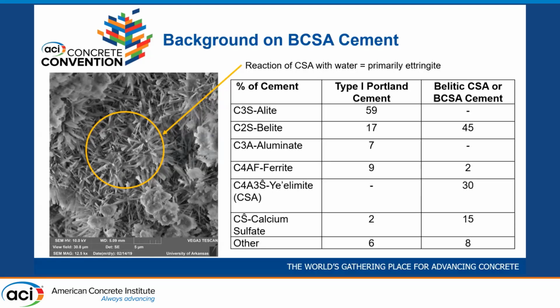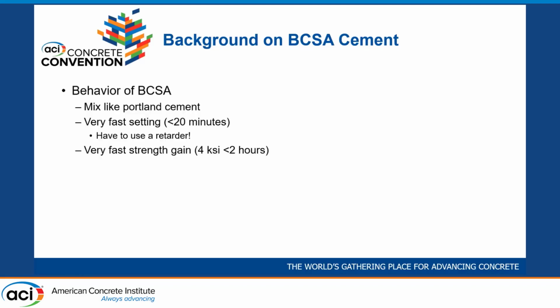So for BCSA cement, I've got a comparison here of Portland cement and BCSA in terms of their composition, what cement compounds are in them. And so for BCSA, you can see over here it has about 30% CSA. And actually, it has more belite than CSA, so about 45% belite compared to about 17% in Portland cement. And so that belite kind of slows down the expansion. It should provide better later age strengths. So that's BCSA and where it stands as a subset of CSA cements in general.